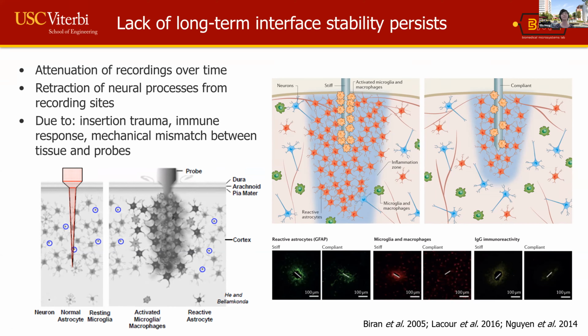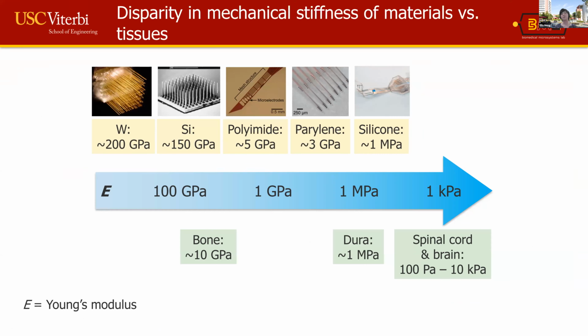So here's a chart that gives you a sense of what we can do as far as improvement by changing the backbone from something like a stiff metal or silicon to a polymer. We gain about a factor of 100 if we're moving to a polyimide or parylene. We can do better by going to silicone, but silicone is not necessarily a great engineering material to work with at times to build certain types of devices. And so most of the field is kind of stuck with polyimide and parylene at this time.